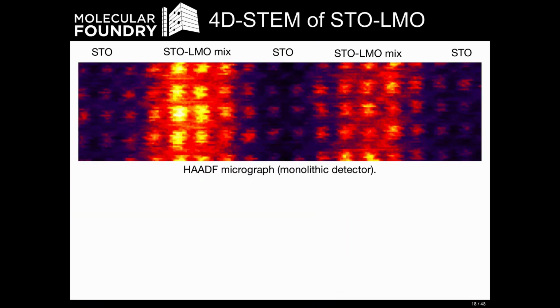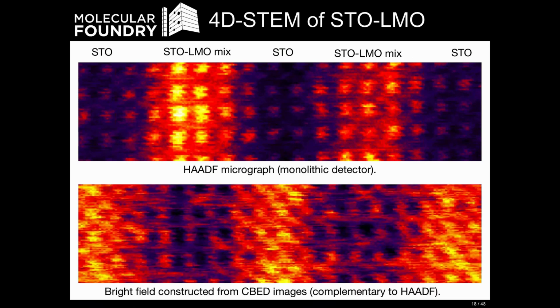If you look at the conventional experiment, the 4D-STEM experiment at the top, you get the HAADF, a conventional image, excuse me. Simultaneously, we record those 4D-STEM CBED images. What I've done here at the bottom is sum up all of the pixels on the center disk. This forms a sort of bright field image, and it's complementary to the HAADF image. You can see a huge amount of streaking along the beam direction. That streaking is because this is before we had synchronized our camera to the STEM scan coils, but we've since solved this issue.